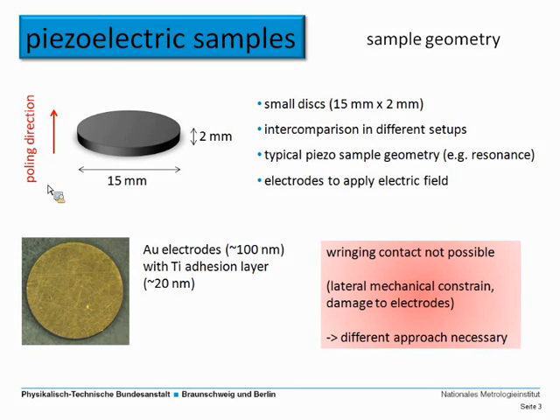Another big difference compared to the gauge blocks is that we have to have electrodes to apply the electric field to the sample. So both circular faces, the top and the bottom, have to be metal covered with some metal composition. We are using a titanium adhesion layer and then 100 nanometers of gold roughly as an electrode, and this is what a microscope image of one of those samples actually looks like.